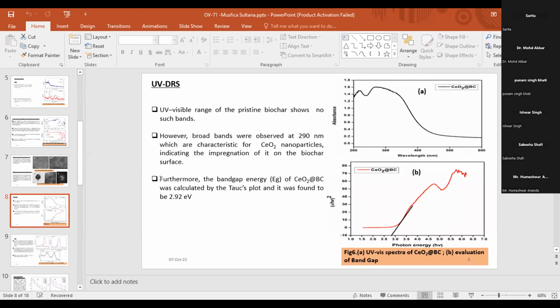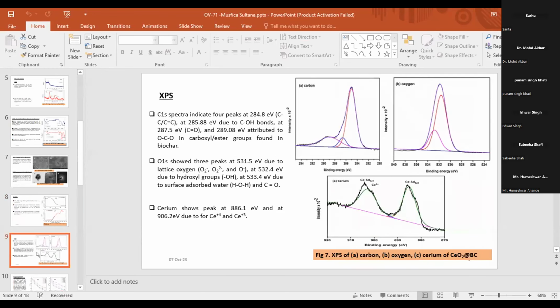From UV-DRS, when done on the pristine biochar, it shows no peaks, but in cerium oxide biochar it shows a peak at 290 nanometers, which is because of the cerium particles, indicating their impregnation on the biochar surface. Further, the band gap is calculated from it, and it is found to be 2.92 eV for this material.